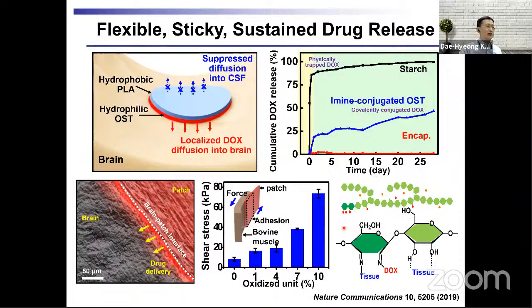For example, if we do not use the oxidization, then most of the doxorubicin molecules will be just physically trapped. And these physically trapped drug molecules can be released easily. For example, within 1 or 2 days, almost 80% of the loaded drug will be released if we do not use the OST film. But if we use the oxidized starch film, then due to the conjugation, sustained long-term drug delivery can be achieved. According to many literatures in cancer treatment, rather than intense burst release of the drug, long-term controlled drug delivery is much more beneficial for the treatment of cancer. So this is more ideal than this kind of burst release.